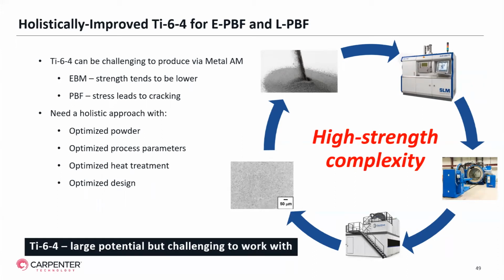Works very well, but the strength tends to be a little lower out of an electron beam melting machine. So for many aerospace applications, it's not quite good enough. On the laser powder bed fusion side, typical Ti-6-4 materials can tend to crack in certain circumstances. So again, it can be challenging with some geometries to make a part that has the strength you need and yet doesn't crack.